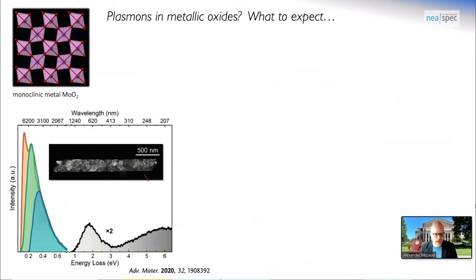Most importantly, the quality factor is described, at least in the case of plasmon polaritons, by the ratio of the frequency to the frequency-dependent scattering rate. This is very important for correlated electron materials to get some inference of the lifetime of quasi-particles. It's actually encoded in the polaritonic response of a 2D metal, whether that 2D metal be graphene or whether it be an oxide.